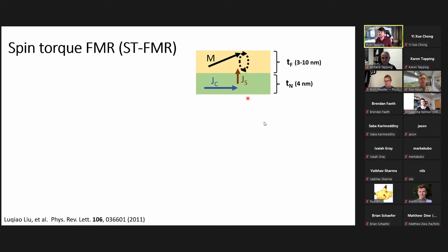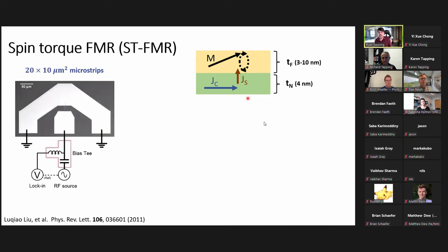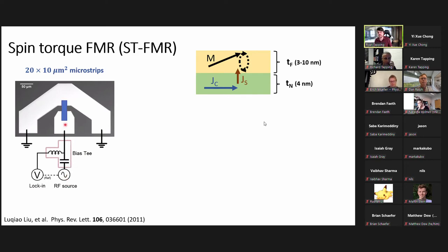The precessing magnetization causes a resistance change due to magnetoresistance effects. Running an RF current through the device with the resistance changing due to magnetic precession, you end up getting a DC mixing voltage out of it. Experimentally, we use an RF source and fabricated bar samples — 20 by 10 micron microstrips. Using contact pads, we run the RF current through and measure the DC voltage using lock-in detection. We sweep an applied field at 45 degrees to the bar to get a measurement.